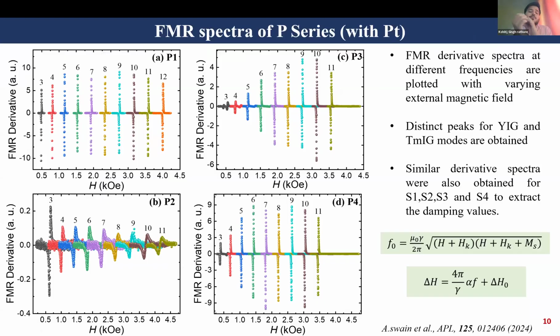These thin films were then magnetically characterized using flip-chip-based broadband FMR, where you place the sample on the flip-chip CPW, and during the absorption of the spectra, these derivatives are plotted with the corresponding FMR signals of the P1, P2, P3, and P4 samples. These derivatives are then fitted with the Lorentzian equation, where we take the zero-crossing point as the resonance field, H_res, and the peak-to-peak distance as delta H.